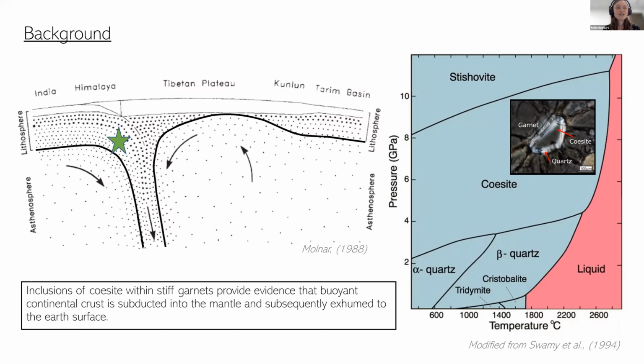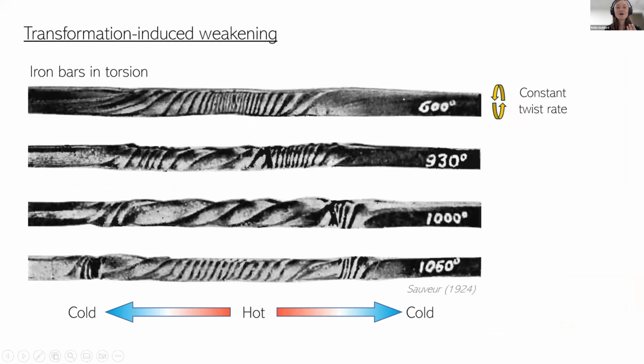There's not really been much research on what happens when you go through a phase transition in geological rocks, but there's been a lot of research currently in material science. This is an example of a really good experiment, which I love from material science, from back in 1924. They had iron bars and heated them up in the center, so you had a temperature gradient from hot in the middle to cold on the outside, and they twisted them gradually at a constant rate. In this top bar, at 600 degrees, you can see that all the deformation is localized on that hot zone in the center.